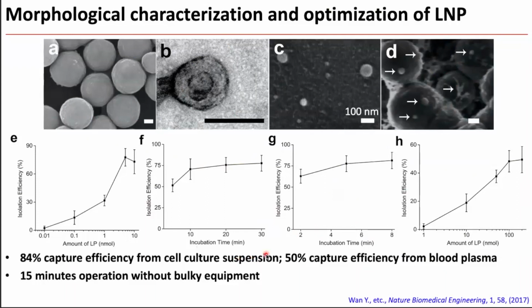One significant advantage of this approach from our point of view is that this is a very fast process. We can run this process within 15 minutes without any bulky equipment. So because of this, it's ideal for relatively small sample volume, from microliter up to a couple of mL. So we think it's good for basically clinical plasma samples.